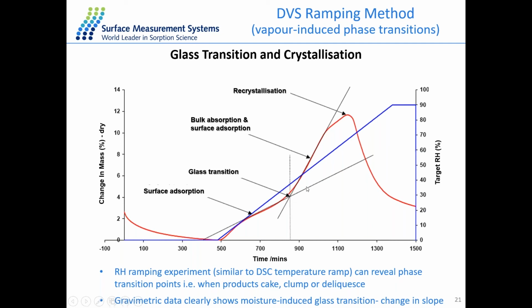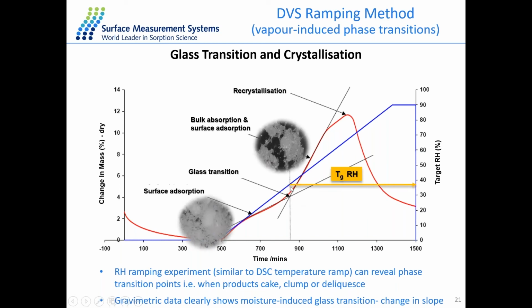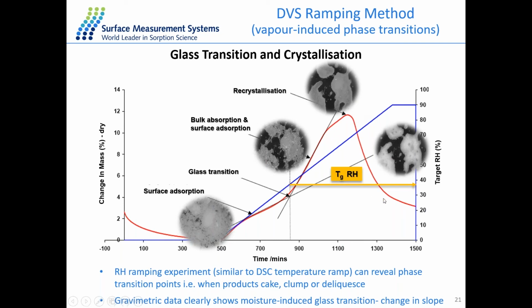And with the slope before and after this change, we can then calculate the glass transition humidity for the sample at a certain temperature. And as we keep increasing the humidity, this sample also goes through crystallization, where the mass will drop dramatically because the crystalline state has a smaller surface area as well as less sorption capacity. So with this single experiment at 25 degrees, we can get the first point for the glass transition of the material, and then the second point for the crystallization of the material.